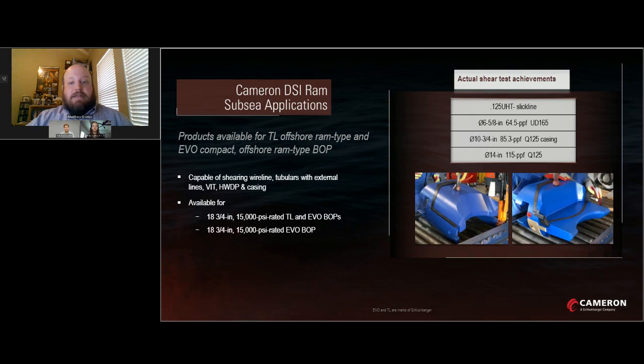It means now we don't need to have 5 heat treat cycles to get the blade portion of the ram to be really strong, but the body of the ram to be less so. By doing this, we're able to shear a 6 5/8, 64.5 pound per foot UD165 tubular. Now we do that at an extremely high pressure, which means that we need to work on some other technology we'll talk about in a moment, linking it to the wheel Sam presented.